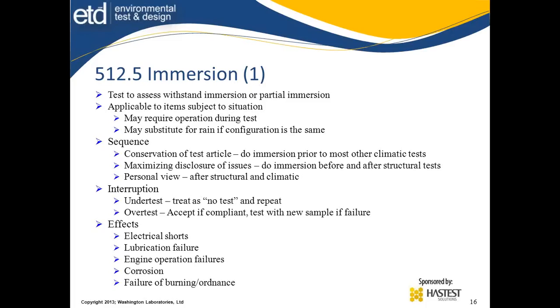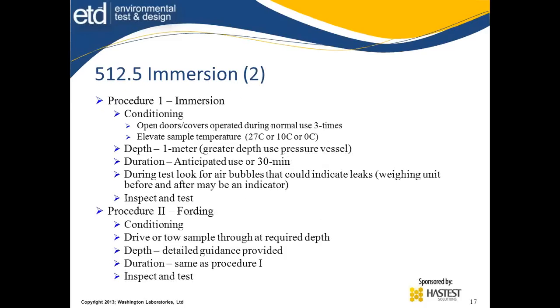Well, I'm supposed to immerse it to 1 meter. If I immerse it to 3 meters, is that an over test? Yeah, could be. High pressure or things of this nature. The effects from electrical shorts, lubrication failures, especially any external lubricants, get washed off. So you might need a water-resistant lubricant if this is going to be a real situation. Engine operation failures, corrosion effects, and obviously contamination of any burning or materials that's associated with ordnance where it has to ignite or things like that, and immersion causes it to deteriorate where it doesn't function properly.